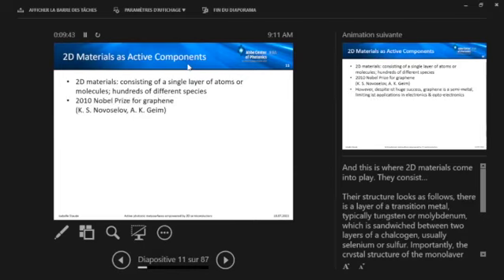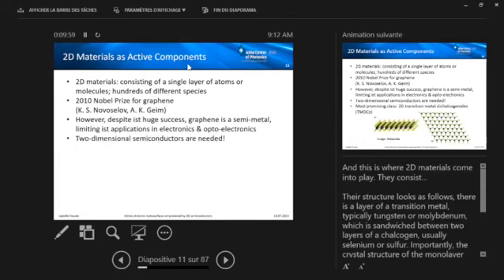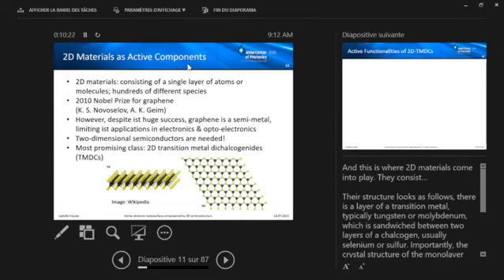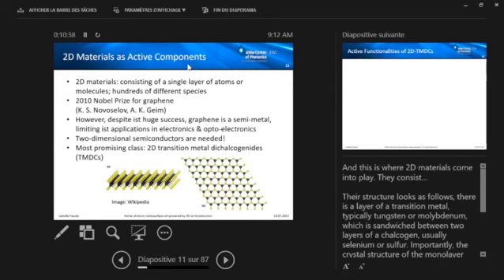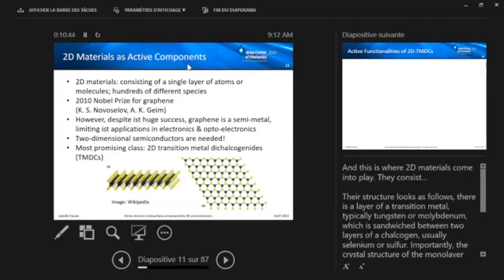It all started from graphene, for which Geim and Novoselov received the 2010 Nobel Prize. However, despite its huge success, graphene is a semi-metal, and this limits the applications in electronics and also photonics. And what we really want for our active metasurfaces are basically two-dimensional semiconductors, ideally with a direct photonic band gap. And the most promising class here are two-dimensional transition metal dichalcogenides, or TMDCs. And they have such a structure that they consist of one layer of transition metal atoms, which is usually tungsten or molybdenum, and this is sandwiched between two layers of chalcogens, basically sulfur or selenium.